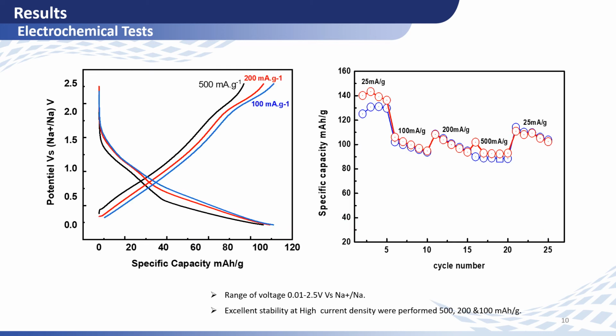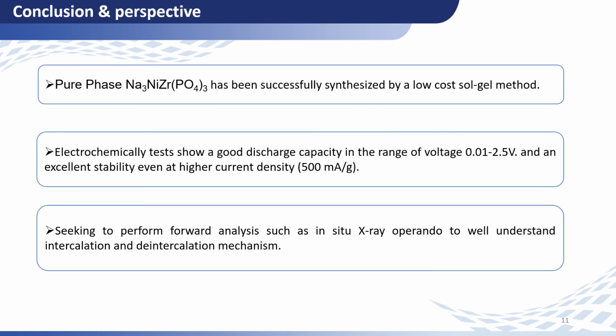This phosphate-based material was also tested at different current densities. We can notice that the capacity still remains 95 milliampere hour per gram at the current density of 500 milliampere per gram, and it's stable compared to the other current densities, which indicates that our material works very well at high rates. So to conclude, the pure phase of sodium nickel zirconium phosphate was successfully synthesized by a low-cost sol-gel method.